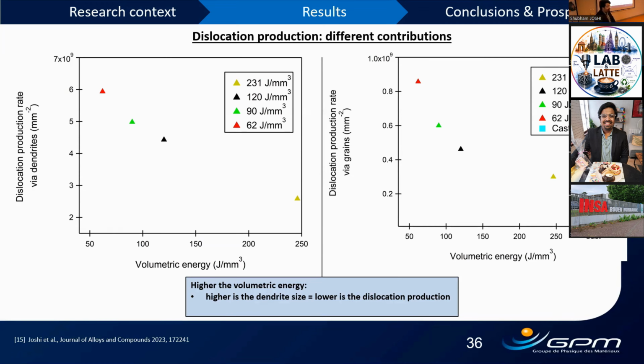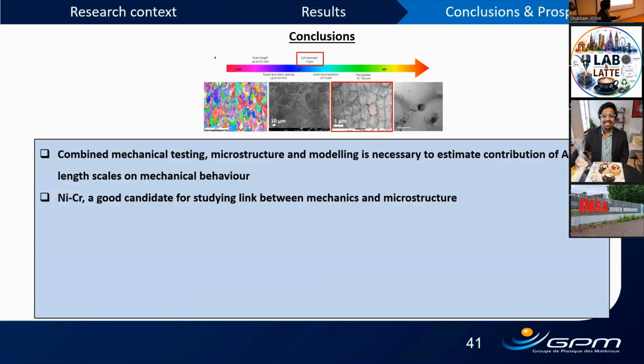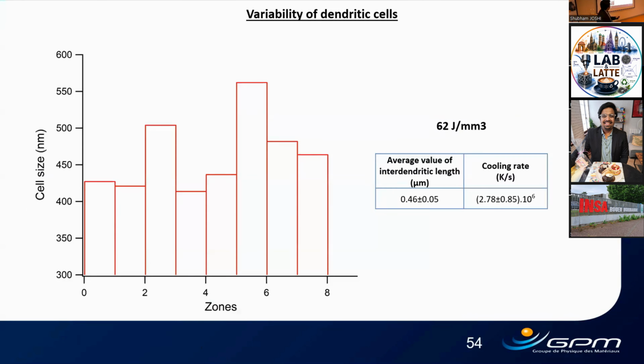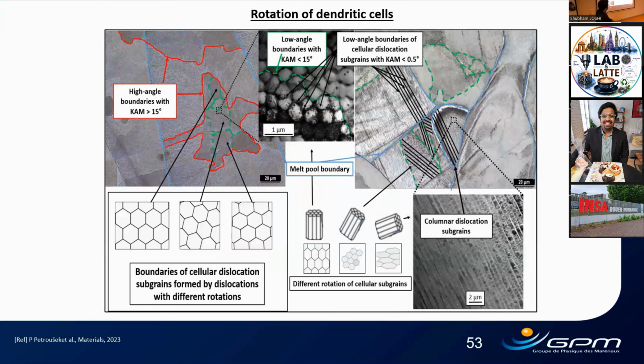So I cannot absolutely answer this, but what I feel is yes, it will. I feel like there should be some influence of the orientation of these dendritic colonies. But having said that, I have an image from the literature. This is from a recently published paper in Materials, and it's a very interesting paper. Sometimes we see that dislocation cells are elongated, but the distance between two walls is similar, and it's just the colony that is rotated. So I don't think that we have to consider different average cell sizes. We can directly take the minimum difference. So it should be helpful for this understanding.